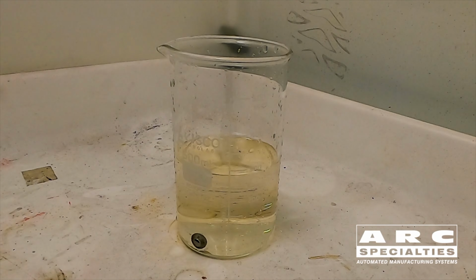So in the video below, we show all three of these conditions occurring at the same time. What we have is a ball bearing, which is a martensitic steel, which is a susceptible microstructure. We have a source of hydrogen, which is the sulfuric acid. And we have compressive stresses. What we've done is we've taken these ball bearings and plastically deformed them in a press. We put them into the sulfuric acid.